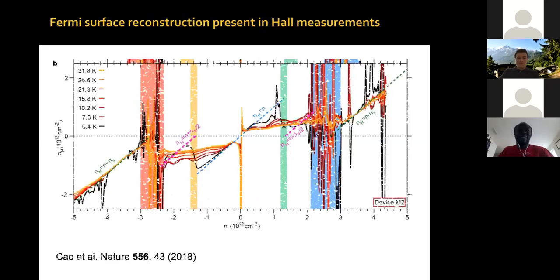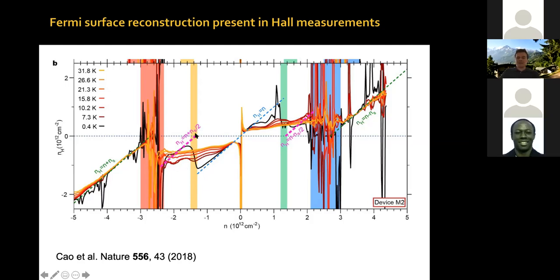So this Fermi surface reconstruction was also present in our Hall measurement data, okay? This is a figure which is in the supplementary information of our original discovery paper. Okay, it's a little bit complicated. Let me just show you the dark trace, because that's the one at low temperature. So we're measuring the Hall density. Okay? We're doing a Hall effect measurement. This Hall density from charge neutrality seems to follow this straight line, which is what you expect based on a capacitance model. But when you reach the correlated insulator state, there is this reset towards smaller Hall density. Okay, it's like the system is resetting back to charge neutrality.